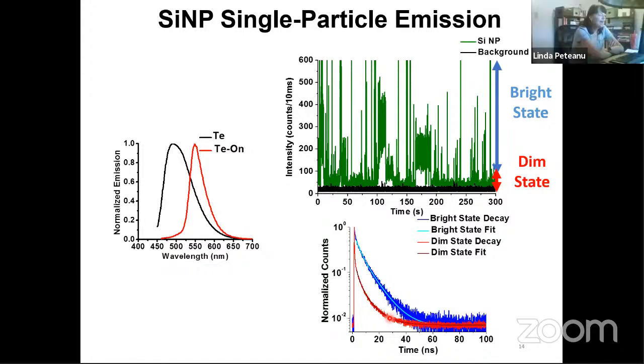Good question. We have found we can fit it. I tend to not fit things with a stretched exponential if I can fit it with two or three exponentials. I don't think that there is anything really that's physically achieved by fitting it as a stretched exponential. So we have fitted, I believe, a bi-exponential in this case. And what we found is that your dominant decay is this IRF-limited, very fast process. And then there is a component which is essentially like that of the bright state emission. There are sometimes additional, longer components that you can get, which we don't ascribe too much meaning to because they're very low intensity. But I don't see any reason why you wouldn't be able to also fit it to a stretched exponential.